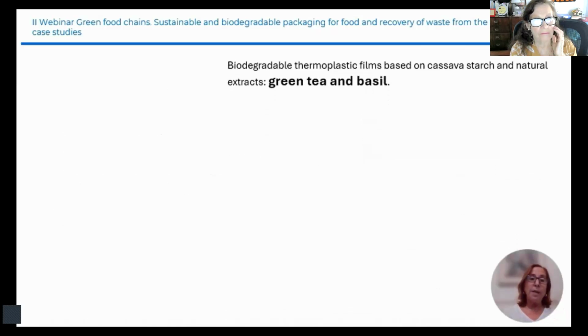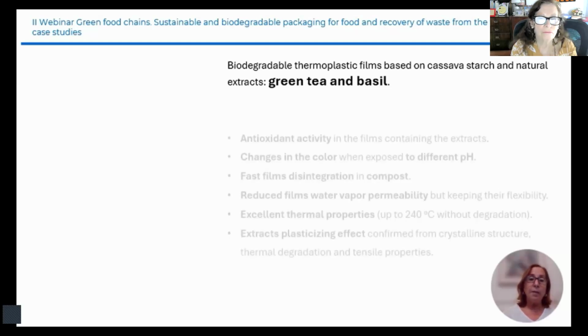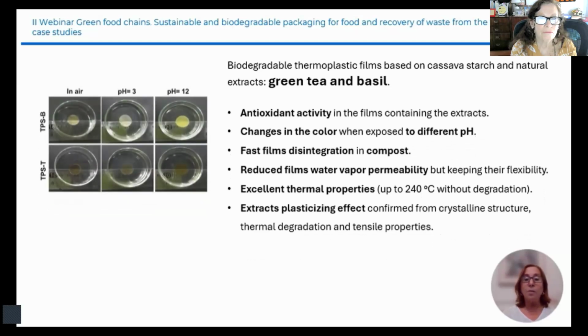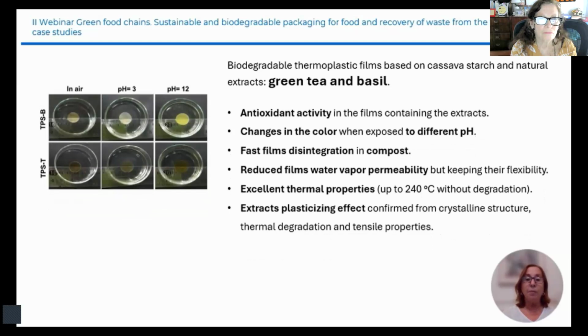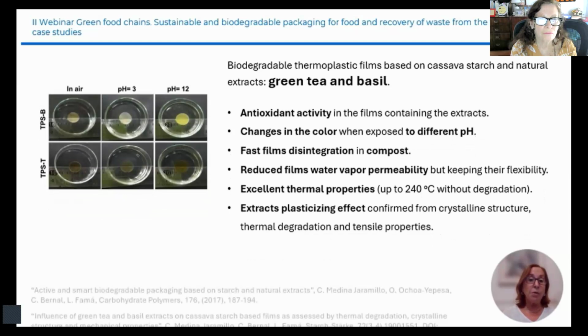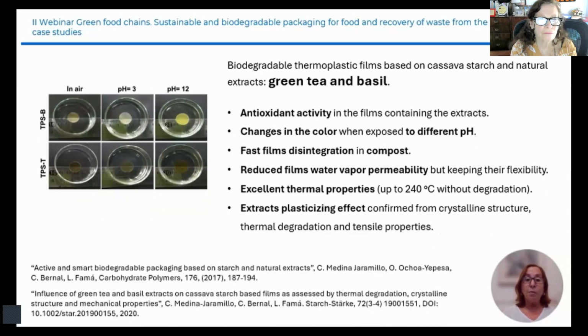We also tried other natural extracts, such as green tea and basil, in the same type of films, and we found antioxidant activity in the films containing the extracts, changes in color when exposed to different pH, fast film disintegration in compost, reduced film water vapor permeability, but also keeping the flexibility of the films, excellent thermal properties, and again a plasticizing effect of the extract. This was confirmed from crystalline structure, thermal degradation, and tensile property results.